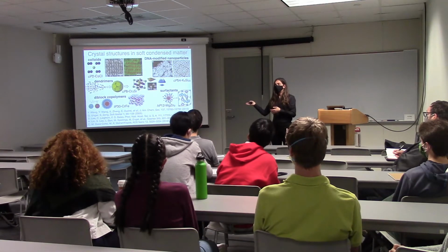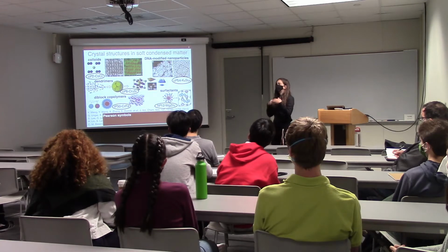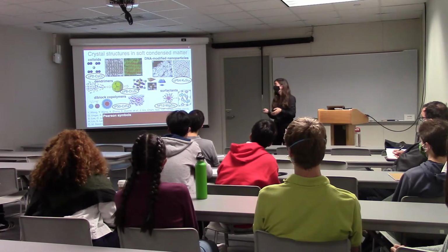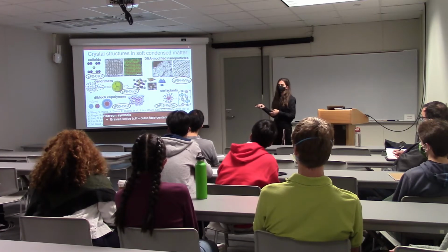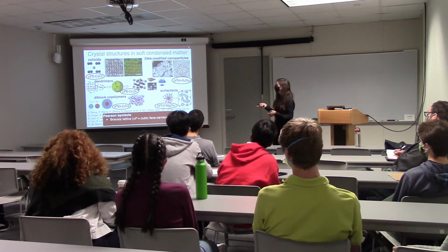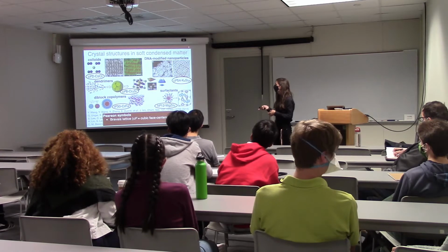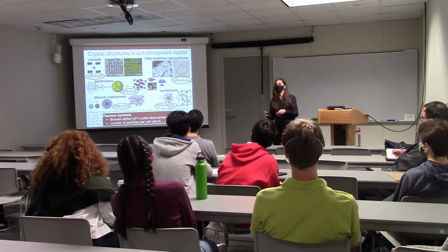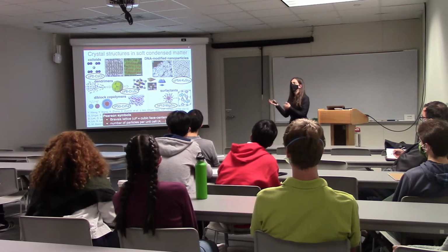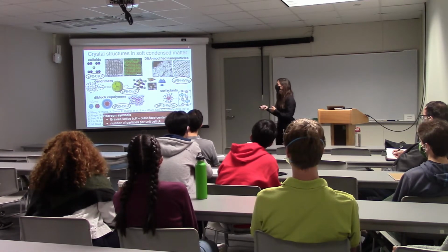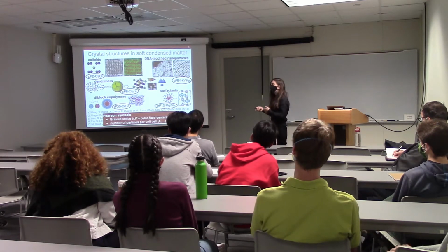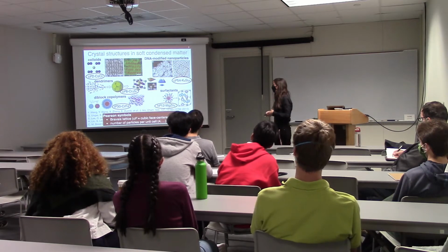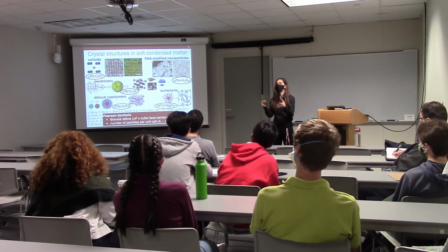The nomenclature that I'm using for crystal structure types leans on that parallel of where the particles are in the unit cell, irrespective of what the particles are. They are called Pearson symbols, and they consist of the Bravais letters. There are 14 of those, right? This one is cubic primitive, tetragonal primitive, and so on, and the number of particles per unit cell. So when I say complex structures, that's the way to measure what I mean by complex. This one may be not too complex with just two particles per unit cell. Here you have 30, that's already a little bit more complicated. And then you have the structure type, the prototypical structure.